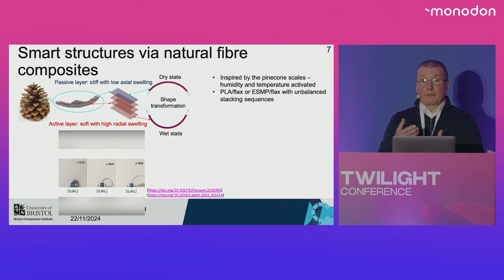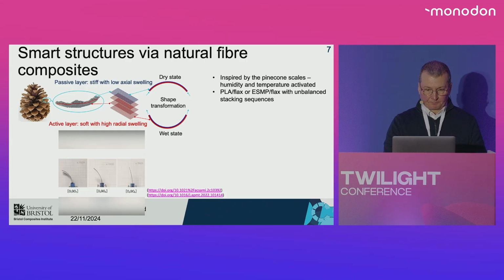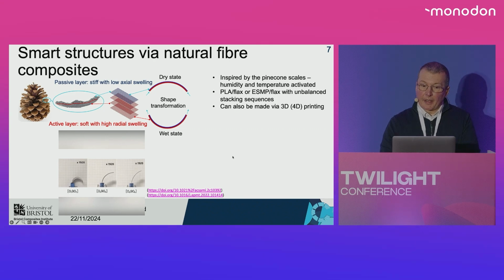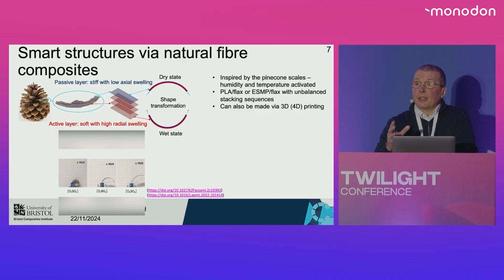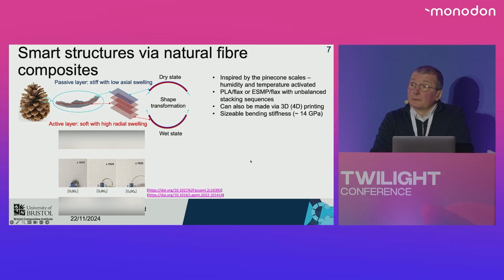And the final curvature depends on the architecture in these types of composites. So you have a one-to-one correspondence between the architecture, the type of composition, and the relative humidity. And the interesting fact is that they can also be made using 3D or 4D printing. By 4D printing, we mean 3D printed structures with materials that evolve over time. And these types of actuators are actually load-bearing. They have bending stiffnesses up to 14 gigapascal, which starts really to be quite interesting, and similar to an equivalent type of composite that you would make using fiberglass.